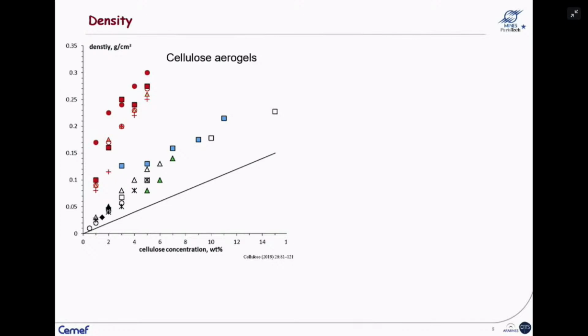So this is an example of the density of cellulose aerogels. And this is the collection of data from literature. Cellulose was dissolved in different solvents. Then different non-solvents were used, acetone, ethanol, and some others. The cellulose of different molecular weights. So everything is combined here. And you see, okay, the density is low, but the density varies depending on the preparation conditions.